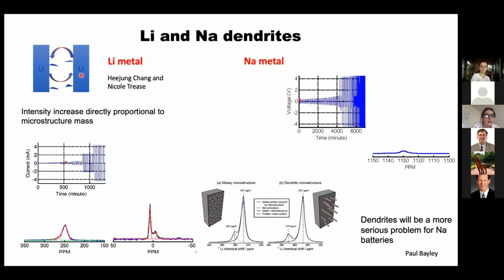We've got lithium on one side, and you're going backwards and forwards, plating and stripping, plating and stripping. And as the current increases, you can start to see the growth of the dendrite. And so there's the peak increasing. And you're simply measuring the effective surface area of the system, because you can't detect the full lithium anode strip.